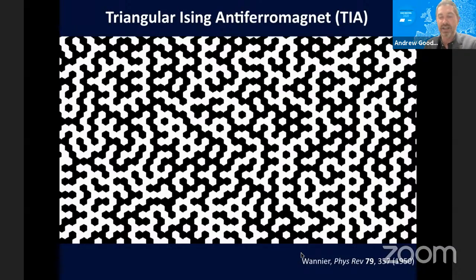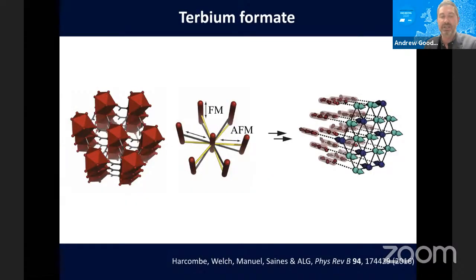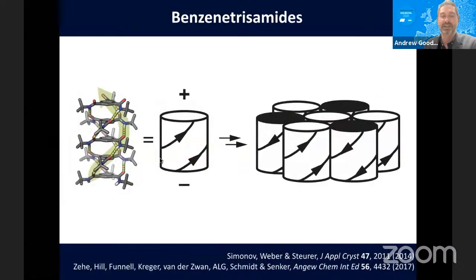I would say that the key thing here is to use the statistical mechanics that's already been developed for these to know what kinds of interactions might favor particular states. And this would come back to things like looking at these. If I'm going to stack polar objects on a triangular lattice, well, I sort of know where I'm going to end up in terms of the structures. So the flip side works. If you want to get rid of it, then why don't I stack this on a square lattice, which isn't frustrated, and then you'll get your crystal if you so want it.